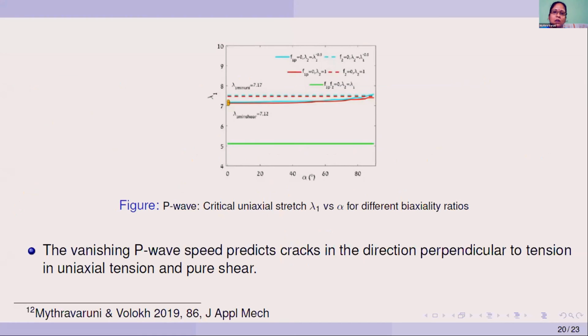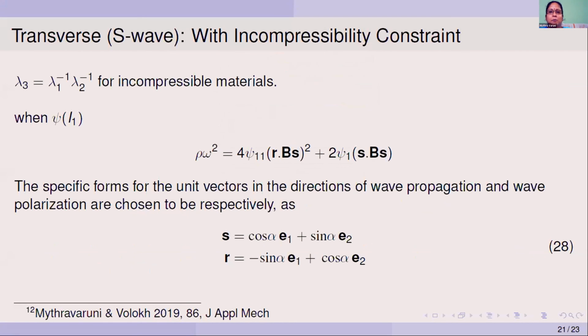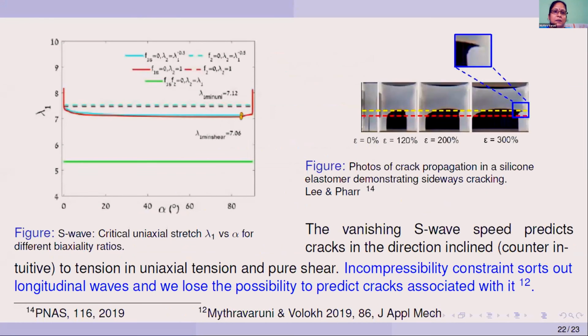the localized crack does not have any preferred direction, whereas in the case of uniaxial tension and shear, this critical value occurs at alpha equal to 0 degrees, and this means that the crack localizes in a direction perpendicular to the applied stress lambda 1. And when we impose incompressibility constraints, we obtain these conditions which we plot here. So you can see the difference between the compressible and incompressible cases here.